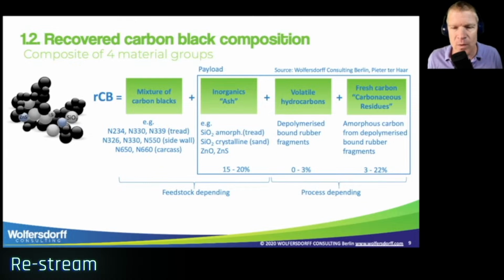The same, we get zinc in the form of zinc sulfide. Zinc oxide is put in the rubber compound as a vulcanization activator. There should not be zinc oxide in the recovered carbon black because zinc oxide is a dangerous good with high ecotoxicity. And if we had zinc oxide in the recovered carbon black, we would have to declare this on the safety data sheet and with kind of ugly looking labels on the packaging.